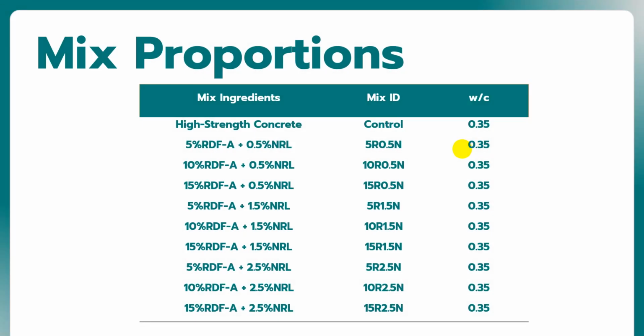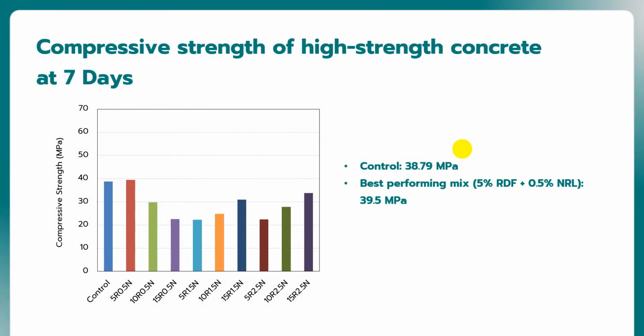For the mix proportion, we fixed the water to cement ratio at 0.35 to ensure the performance of the materials. For the NRL, we add 0.5%, 1.5%, and 2.5%. For the RDF, we add 5%, 10%, and 15%. And we test the compressive strength at 7 days and 28 days.